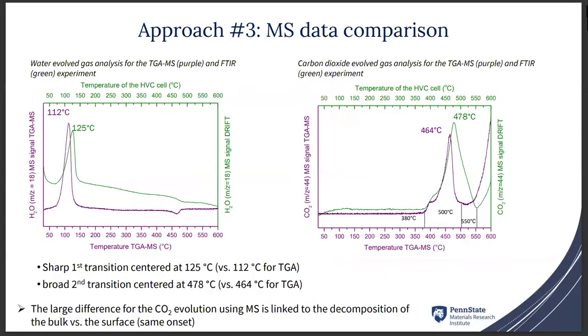The last approach we try is comparison of MS from the TGA and the MS from the FTIR. We can see for the first transition it's in good agreement with the previous approach using the baseline variation, so we find 125 degrees Celsius using the FTIR versus 112 using the MS for the TGA.